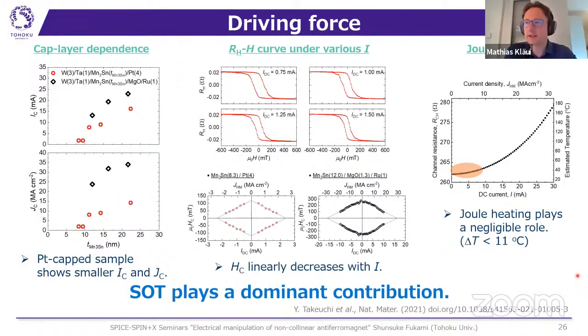And the second, how did you evaluate the actual current densities in the multilayers? What kind of interface resistances, and did you use Fuchs-Sondheimer, or how did you calculate? The estimation is based on the assumption that each layer is a parallel resistor. We evaluate the resistivity of each layer, and from the parallel resistance model, we determine the current density flowing in each layer. Okay, so a parallel resistor model, but the interface resistivity is not taken into account. We didn't consider the effect of the interface. Okay, any further questions?